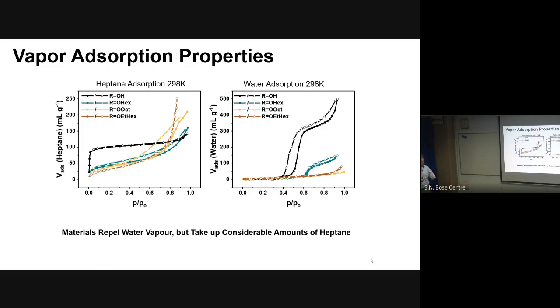When we think that the side chains repel the water, they cannot interact with water. There cannot be any hydrogen bonding or any polar interactions. But the frameworks that have the side chains can interact with the heptanes, for example, because they can rearrange. So the vacant space inside, which is in some cases about 1 to 2 nanometer, has nothing to do with the specific adsorption properties, only for the non-functionalized materials.